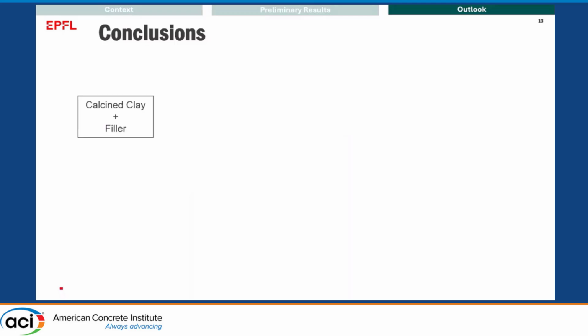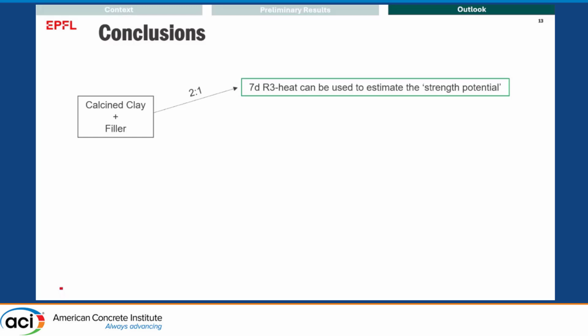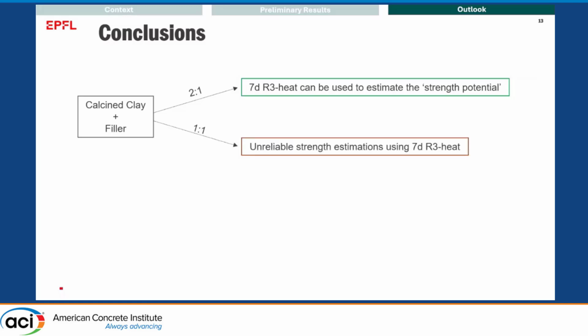So in conclusion, I used calcined clay and filler in different ratios. When I used it for 2:1, I realized that R3 heat can be directly performed on the 2:1 calcined clay to filler blends, and it can be used to estimate the strength potential, or to do the primary screening of the blends. On the other side, for 1:1, I would really not suggest doing that, as there are unreliable strength estimations, and this needs to be explored more via microstructural characterization.